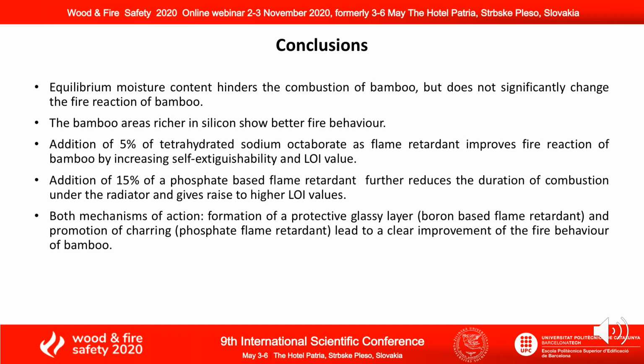The same trend, the addition of 15% of phosphate-based retardant further reduces the duration of combustion under the radiator and gives rise to higher limiting oxygen index values. And both mechanisms of action, the formation of a protective glassy layer, which is the main mechanism of action of boron-based flame retardant, and the promotion of charring, due to the presence of phosphate flame retardant, lead to a clear improvement of the fire behavior of bamboo.